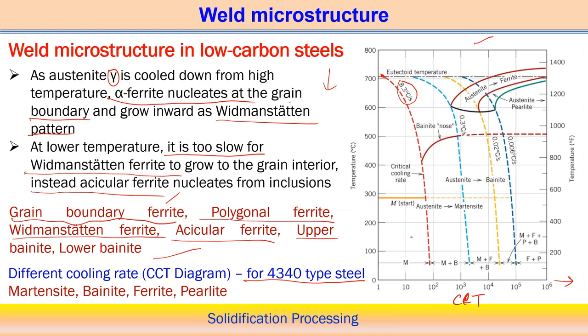Even if the cooling rate is more than that, it indicates the left hand side of this curve. So that indicates the cooling rate is high. When the cooling rate is more than 8.3 degrees centigrade per second, we can expect the martensitic structure. This information we can get from the CCT diagram for this particular steel. For example, even if the cooling rate is between 0.03 degrees centigrade and 8.3 degrees centigrade, in this case we can get a mixture of martensite plus bainite structure. So that we will get as the final structure.